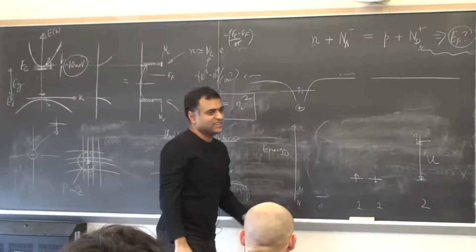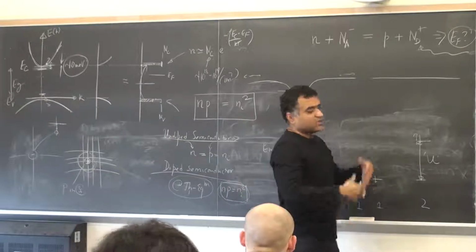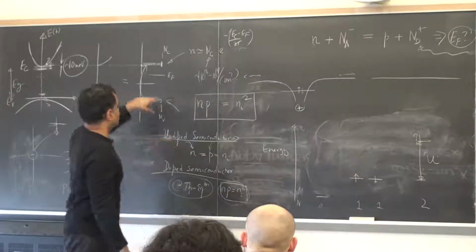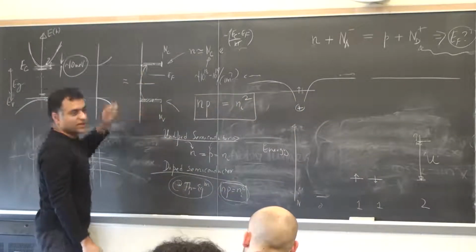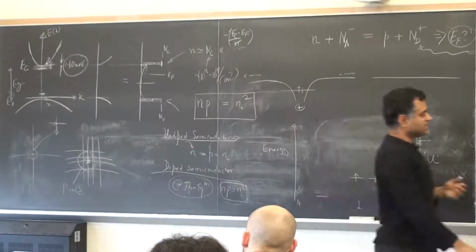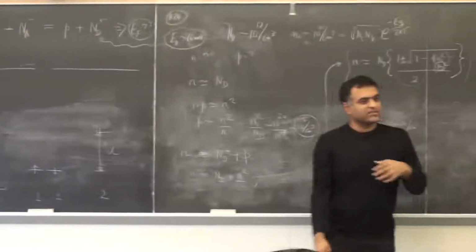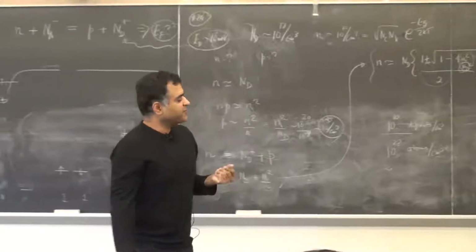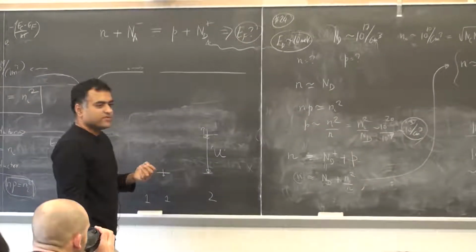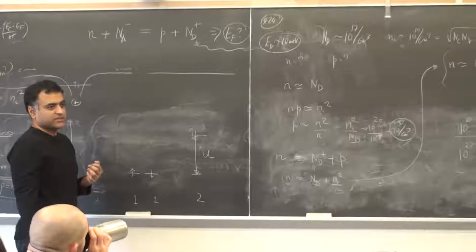I'm talking about silicon or gallium nitride, these materials. That's the parlance. Heavily doped means carrier density is roughly 10 to the power 18 to 19 per centimeter cube, and lightly doped is 10 to the power 15, 10 to the power 16 per centimeter cube.